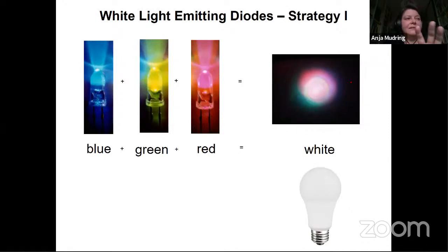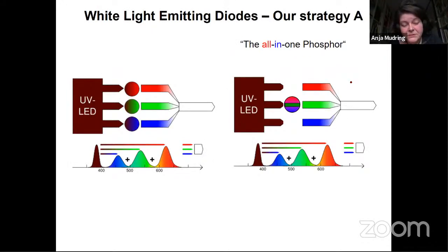And that's not nice because, again, it's not truly white light. And you have the problem, additionally, that the red, green, and blue LEDs degrade differently over time. So the color impression of your light bulb is changing. That is something that you can electronically compensate for, but you still would need 3 different driving circuits for your LED light bulb. So that's not good. So it would be better to have an all-in-one phosphor, which is not that simple, because now we have to have 3 emitting rare earth ions, like you have in the CFL. You saw there we had the 3 different phosphors, the blue, the green, the red, and you combine them. If you now combine all 3 ions in one host lattice, you have energy transfer mechanisms between them.